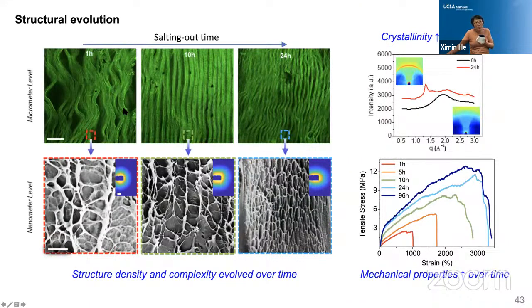Right, so a little bit about the fundamental mechanism. We monitor the structure evolution during the soaking of 24 hours in the salt solution. You can see these microfibers become finer and more aligned. At the same time, this nano mesh grows even denser and more obvious. And then we measured crystallinity increase over time, as well as the mechanical strength and stretchability, without compromising one or the other.